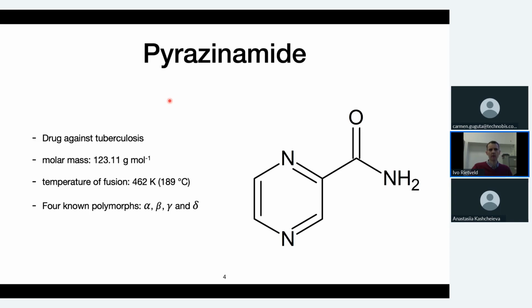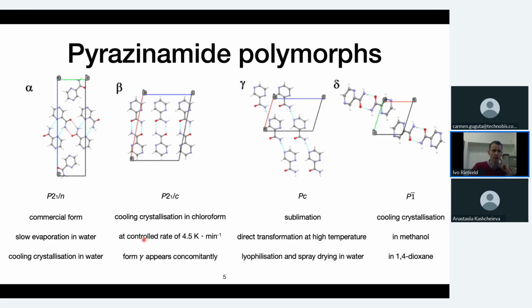So pyrazinamide itself is a rather small molecule. As you can see here, it has a molar mass of 123 grams per mole, so quite small. The temperature of fusion is, on the other hand, relatively high, say 190 degrees Celsius. It's a drug used against tuberculosis. And, as you may have figured, there are 4 polymorphs that are named alpha, beta, gamma, and delta, which I have shown here. So these are, say, the main structural elements that you can find in the structures of these different polymorphs.